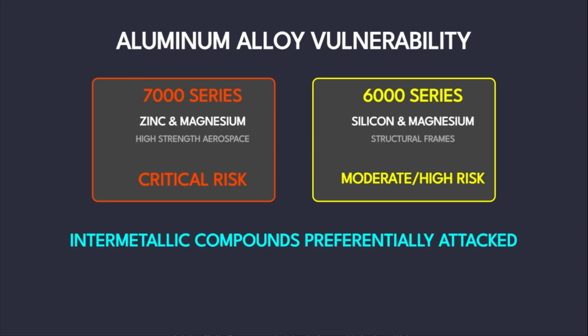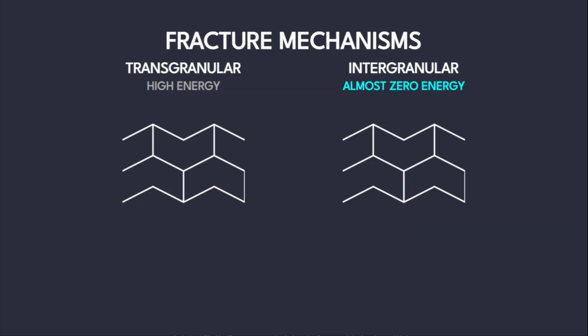The presence of alloying elements can sometimes create intermetallic compounds that gallium preferentially attacks. This makes the use of gallium near any engineered aluminum component extremely dangerous, as the specific heat treatments used to harden the metal often create the very grain boundary conditions that gallium is most efficient at infiltrating.